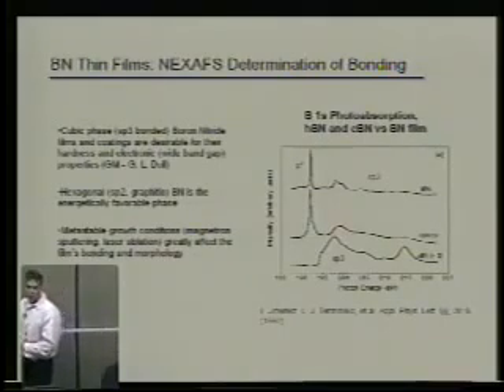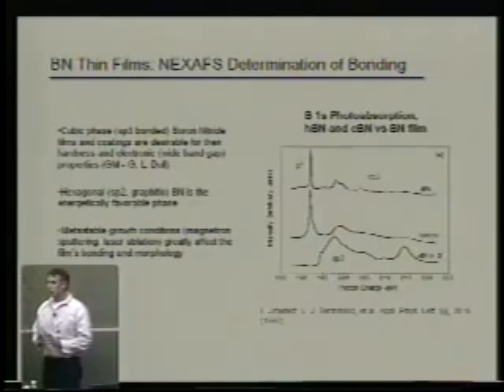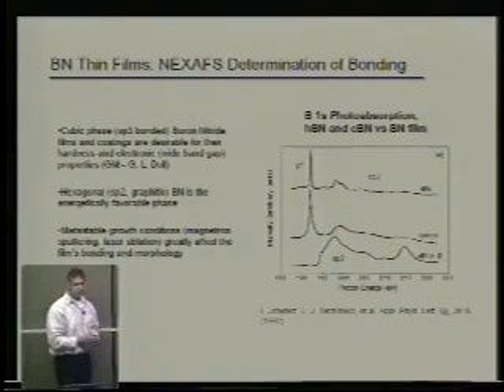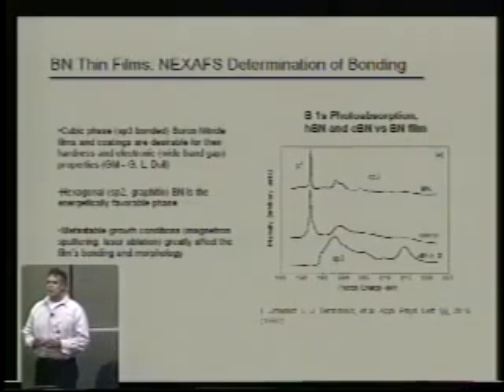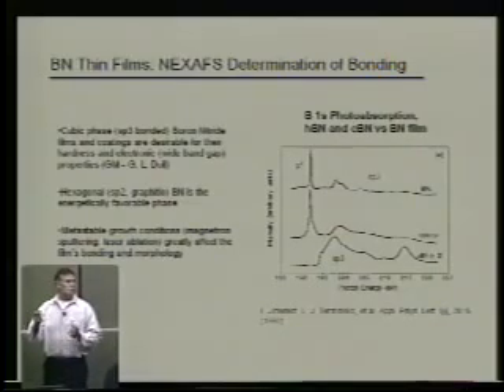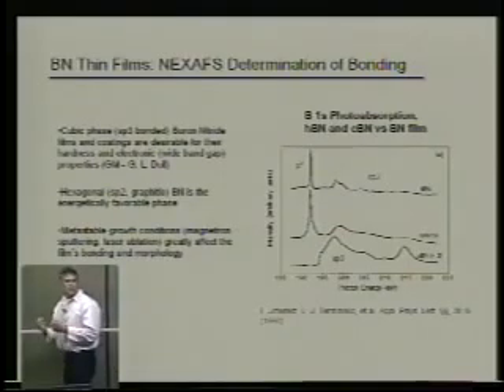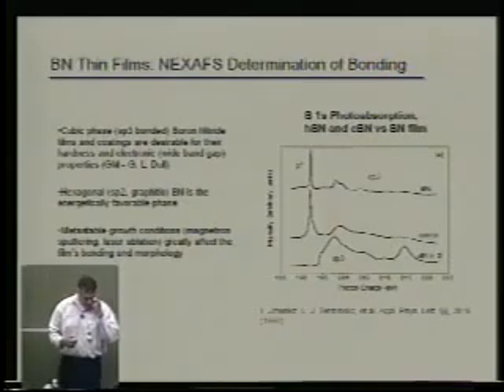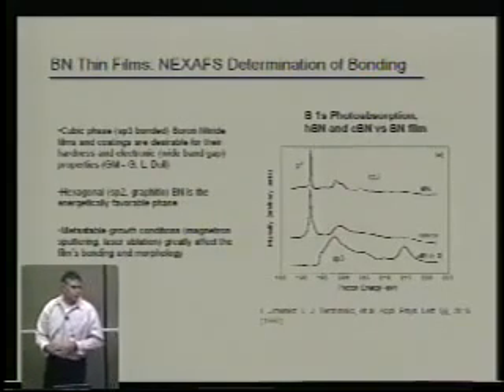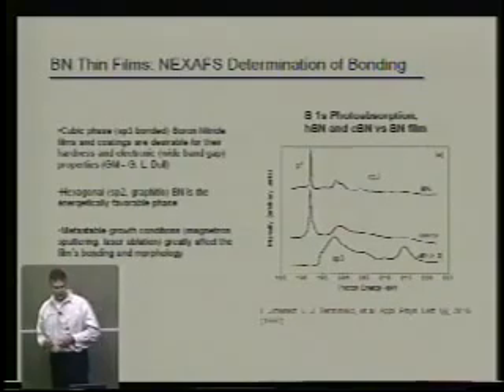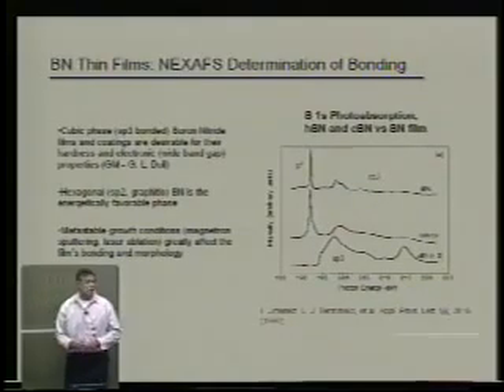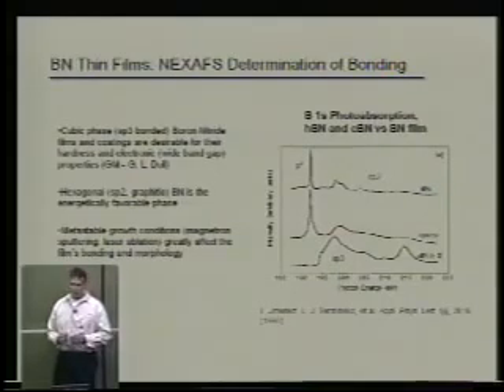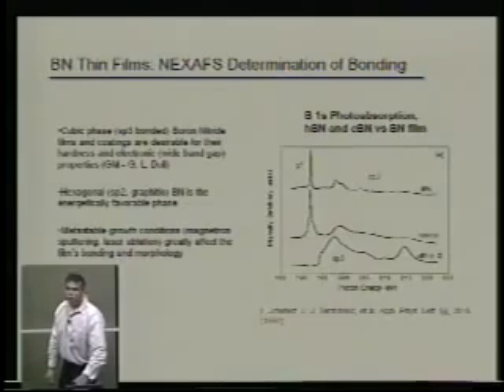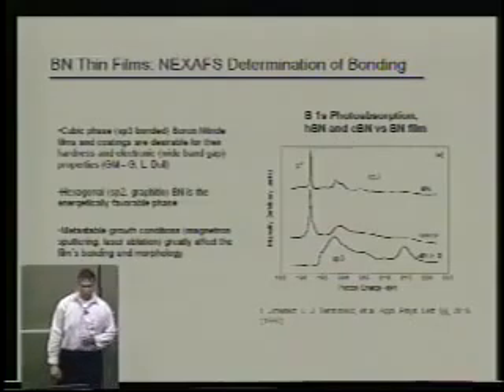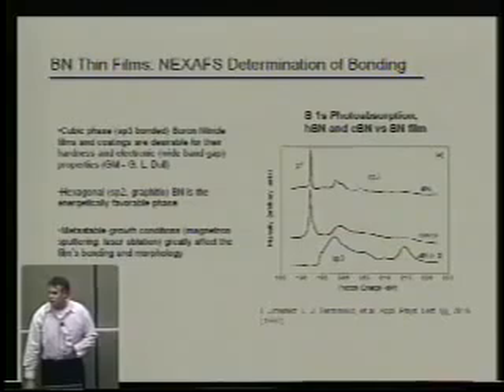So just by looking at the bonding coordination, you can see that the absorption edges of these two materials are completely different. But there's one more thing going on here, is that in some cases, the ejected electron can still see the core hole. And these are called final state effects, that it forms like a bound level. So the very sharp, what's called pi star, if you work in the NEXAFS field a lot, you're going to hear pi star, especially with carbon and boron nitride. This is a resonance feature, akin to an excitonic feature. So you actually get a feature that's associated with the final state of the system, not the initial state of the system. So you can map out things like excitonic features using the X-ray absorption technique, as well as getting information on bonding.